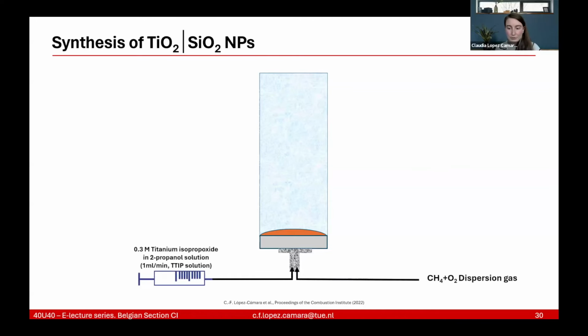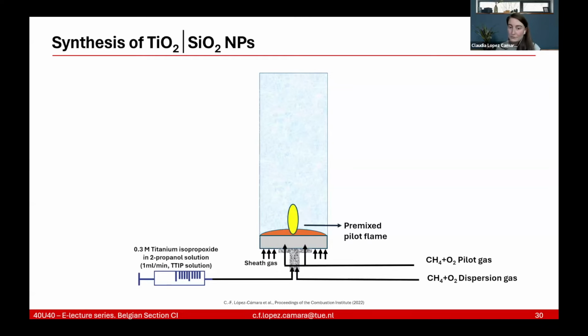And we inject dispersion gas, which is oxygen and methane, and a precursor or reactant for titanium, for creating the core nanoparticle of titanium dioxide, which is TTIP solution. We have sheath gas, we have a pilot gas, because if you remember, I mentioned that you have a pilot methane oxygen gas in order to ignite your precursor. And as soon as we put that in, we see a premixed pilot flame, because we are using, in this case, a spray-syn burner. And then we have core titanium dioxide nanoparticles.